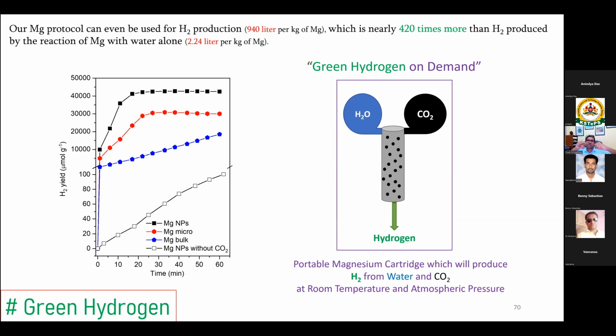When it's magnesium and water, it forms a magnesium hydroxide layer on the magnesium, and then internal magnesium atoms cannot react with water. But when I form magnesium basic carbonate in presence of water plus CO2, that layer can dissolve into the water, and then the fresh atomic layers of magnesium are ready to react with water. That's why the entire magnesium gets reacted with water very fast. You look at the kinetics - within a few minutes you produce a huge amount of hydrogen.